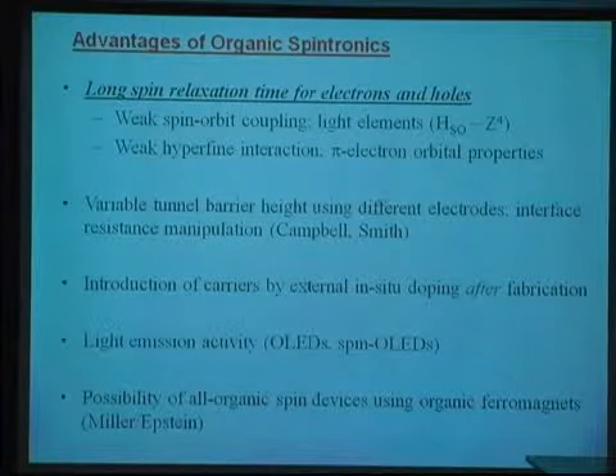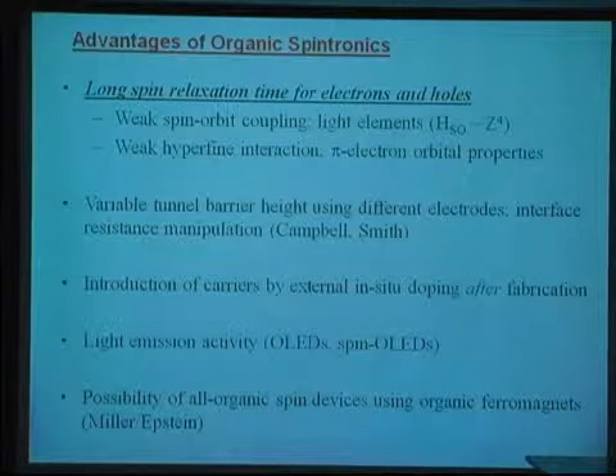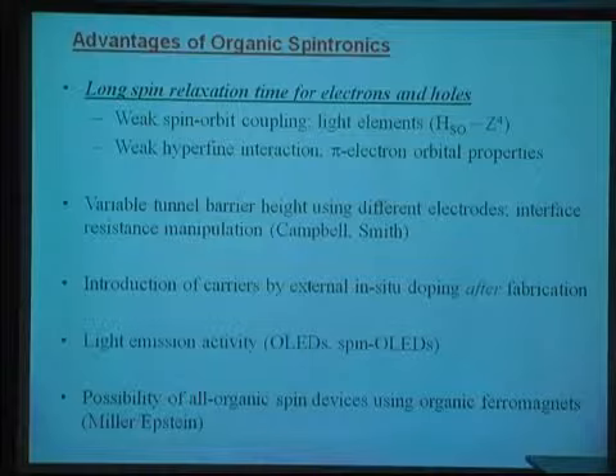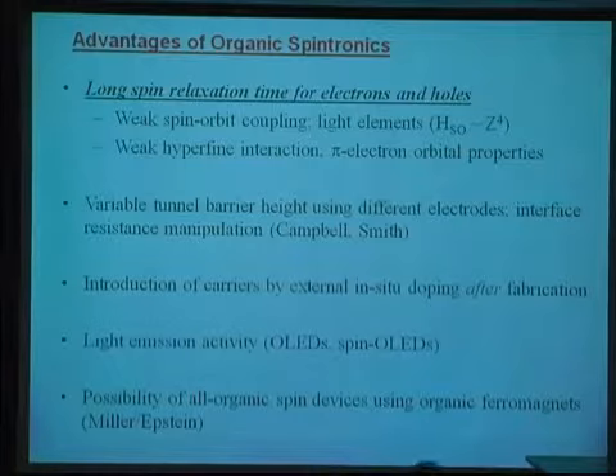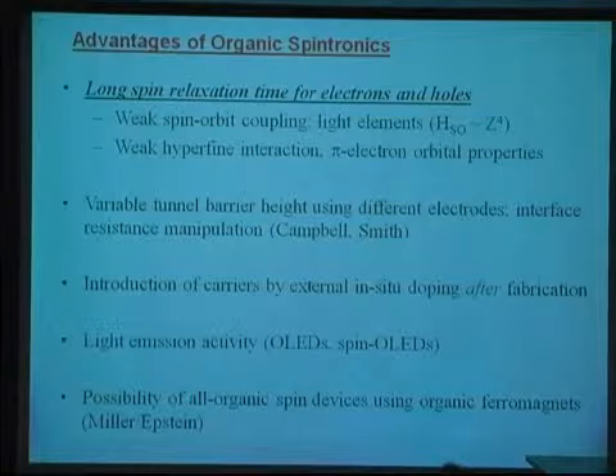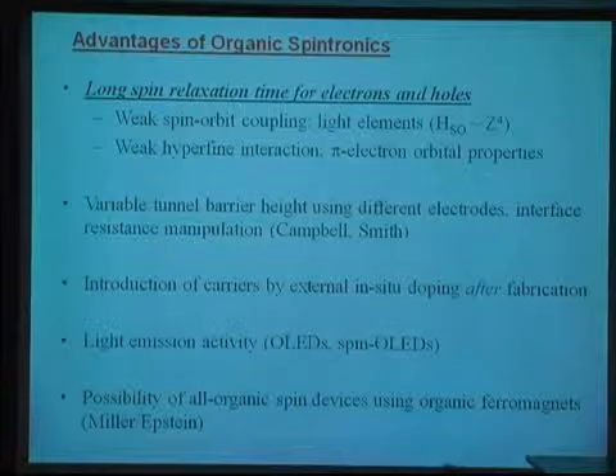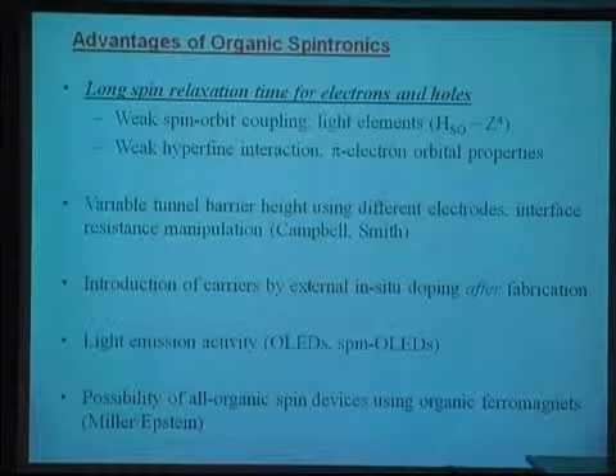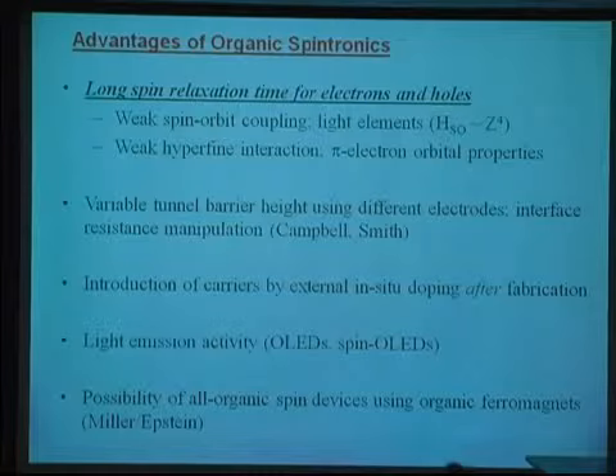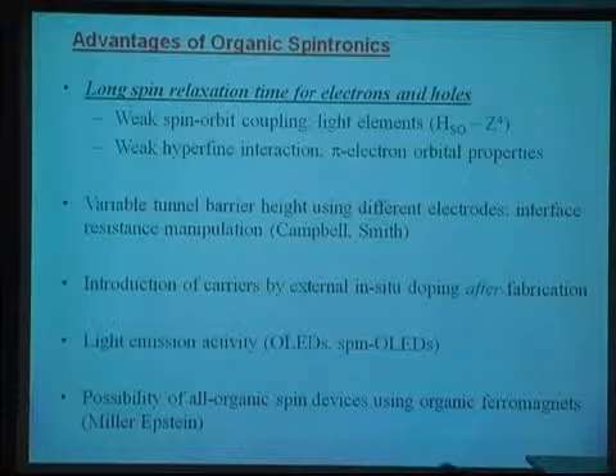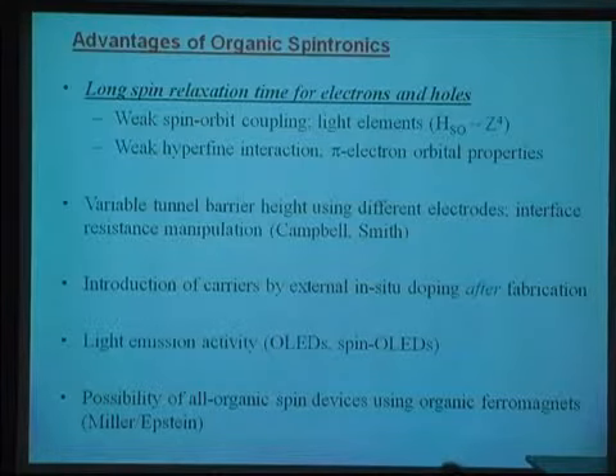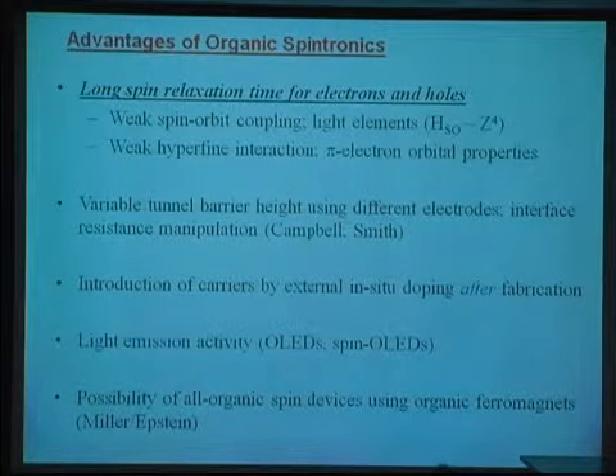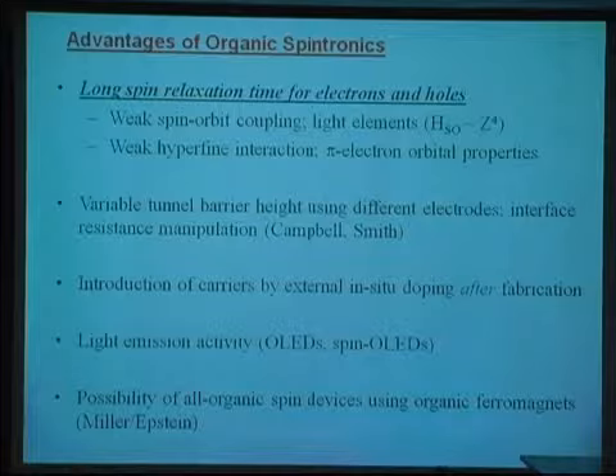Okay, so what are the advantages of organic spintronics? Everyone knows this sentence very well because it has been repeated many times. The spin relaxation time in organic material is very long because of the weak hyperfine interaction and also weak spin-orbit coupling in the materials. The second advantage is that when you deposit the organic film on top of the ferromagnetic materials, you form a tunneling, insulating barrier at the interface naturally. So this interface can help you to overcome the resistance mismatch problem that we talked about in the previous slide.